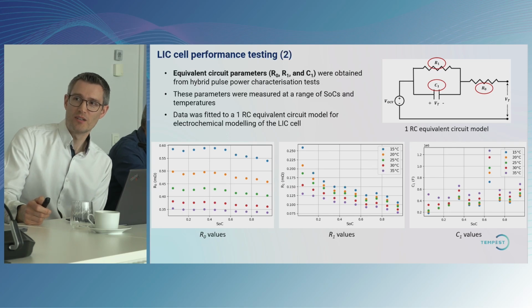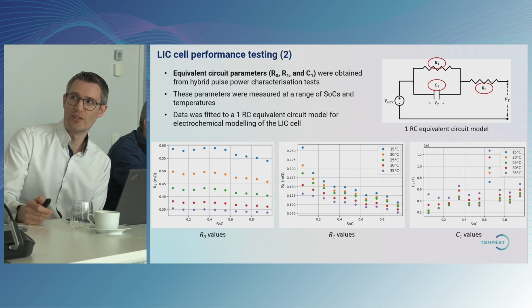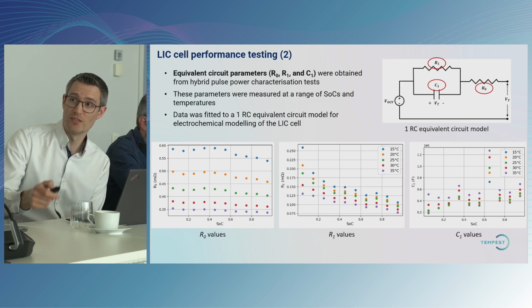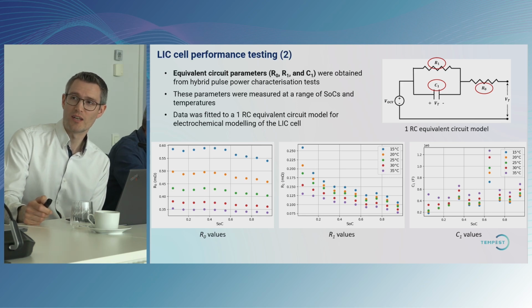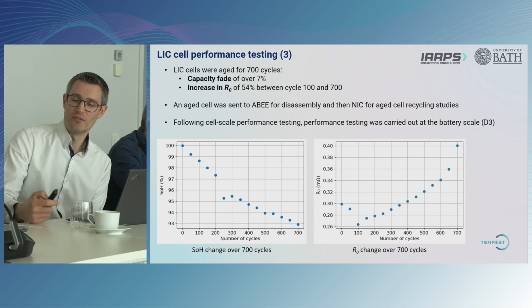So beyond that, we did some characterization of the Thevenin equivalent parameters, so the internal resistances and the capacitance terms to parameterize a Thevenin model. And we did that at a range of different states of charge and a range of different temperatures. So again, you can see all the results here, and that allowed us to build up a nice representation of the lithium-ion cells in the digital domain, and fed our modelling work.